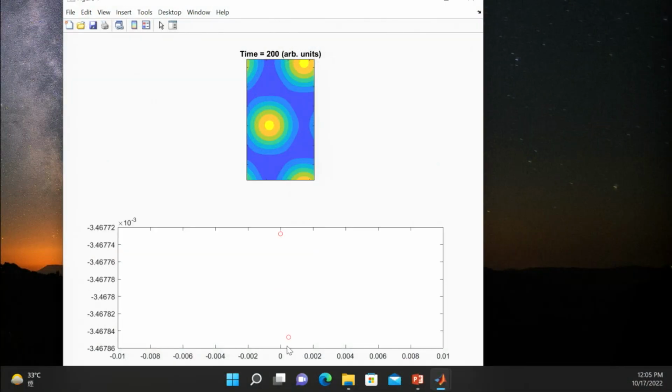All right, so the horizontal is the strain. So positive, which means tensile strain, right? Yes, that's tensile strain, exactly. So of course, for the linear elasticity, we are expecting that when k equals 1, or 4 pi over square root of 3, that should be the energy minima. But actually, the minima is somewhere very close to 0.1% of strain, right? So if you carry out this calculation, you'll see what's going on here.